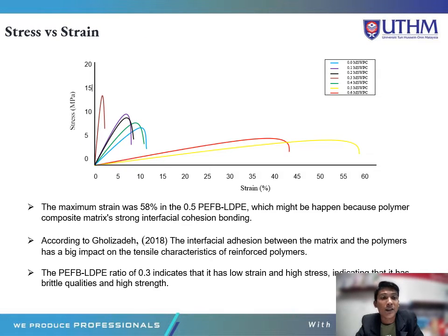This graph shows the stress versus strain for different samples of PEFB LDPE polymer composite. The maximum strain was 58% in the 0.5 PEFB LDPE sample, which might happen because of strong interfacial or cohesion bonding in the polymer composite matrix. According to Gholizadeh 2018, the interfacial adhesion between the matrix and the polymers has a big impact on the tensile characteristic of reinforced polymer. PEFB ratio 0.3 has low strain and high stress, indicating that it has brittle qualities and the highest strength.